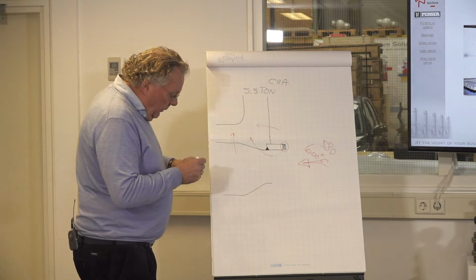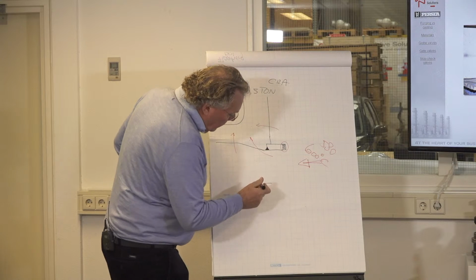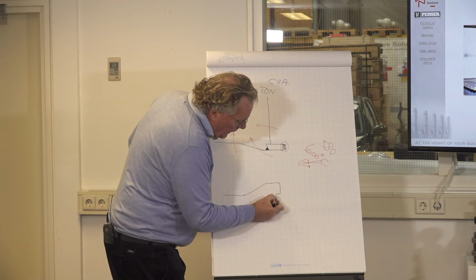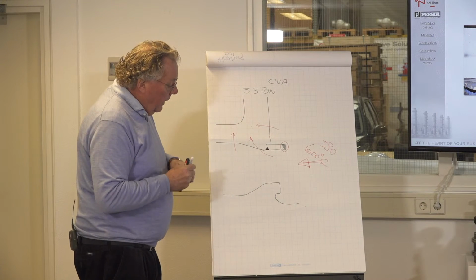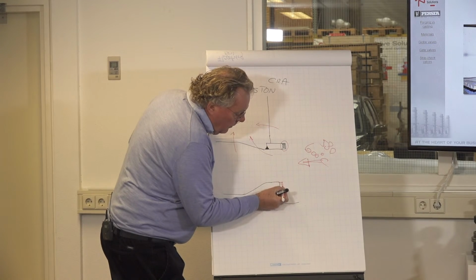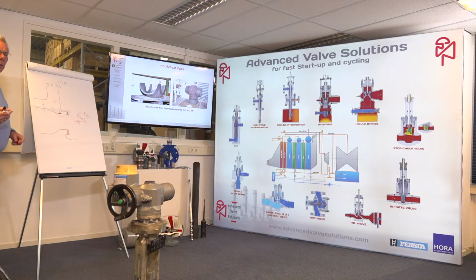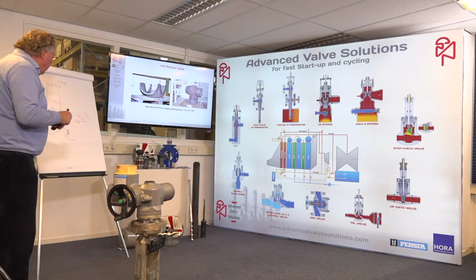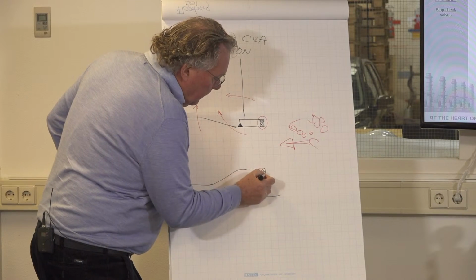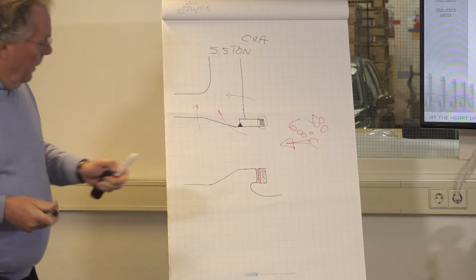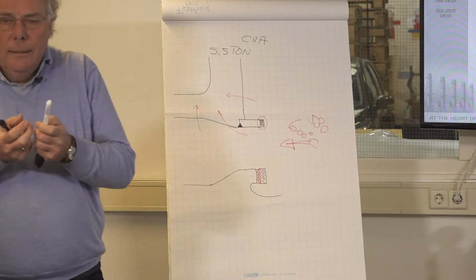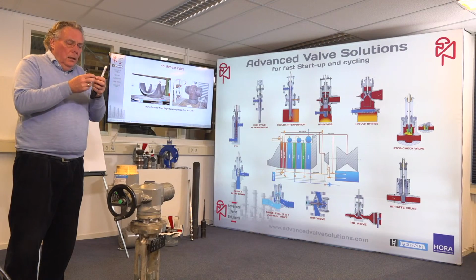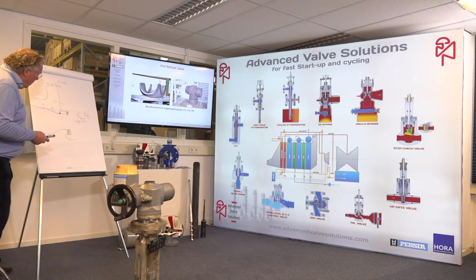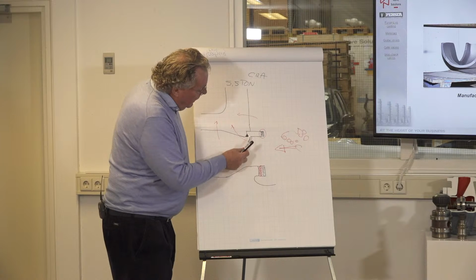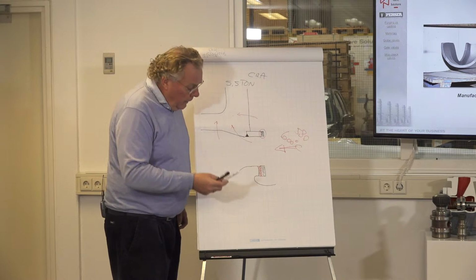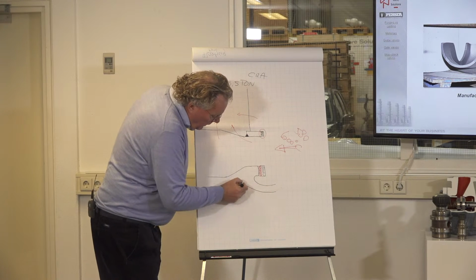How do we solve it? You can imagine that if I do have an integral seat, if I have this material completed and my valve is like this, I now take a big layer of a buffer material, a butter layer of, let's say, Inconel or something like that, and on that buffer layer I now place my stellite. Well, that butter layer, this red layer, is flexible, so that red layer can absorb the differences in expansion of the different materials, but at the same moment the complete heat flux can go into the valve body instead of just through this weld. So there is much more heat going in, in combination with a valve body which is, due to the material, much thinner.